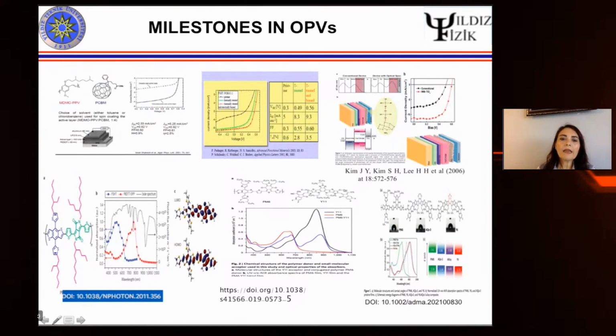Later on, Franz Padinger, who was also from our group, was studying P3HT:PCBM. This was polyphenylene vinylene, and now this is thiophene. He built solar cells using P3HT, poly-3-hexyl thiophene, and PCBM. And there, after fabricating the device, he measures the efficiency and then puts it on a hot plate and applies a certain thermal annealing. As a result of this thermal annealing, he realizes that the efficiency increases. Here it was 2.5, and by replacing the material and also applying this post-production treatment, this terminology now appeared in our lives. So the efficiency was improved to 3.5%.